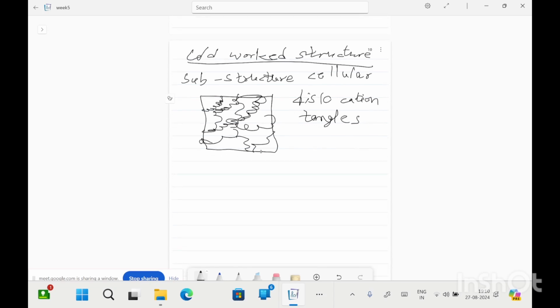So the formation of cellular substructure depends on different parameters. First is the material: if the material can be easily deformed, then dislocation cellular substructure forms readily and increases the strength significantly. If the material is hard, then the formation of cellular substructure is also difficult. Second is the strain. With increasing strain, the cellular substructure formation increases. Third is the strain rate. If the strain rate is high, then the formation of cellular substructure is more favored. Then temperature of deformation.